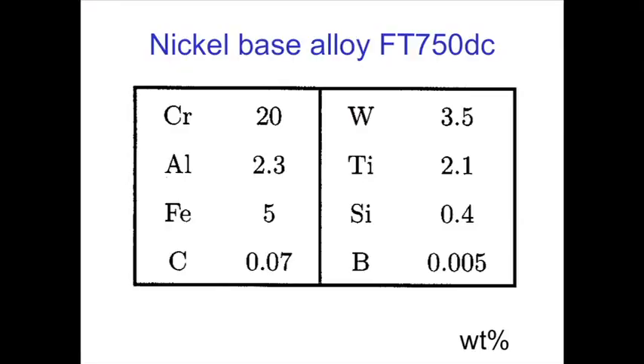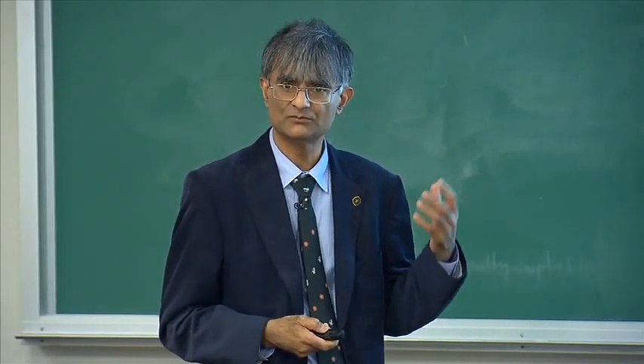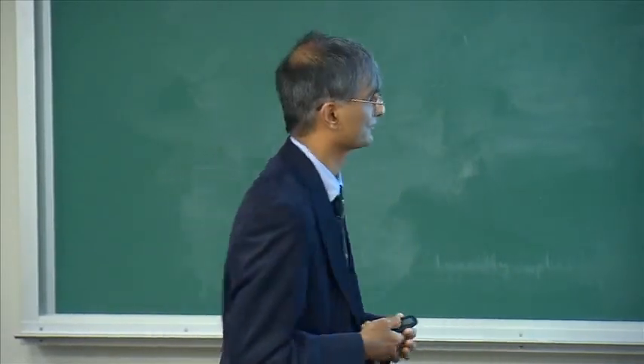So again, we have a very large quantity of data, and we designed a steel using the neural network, not a steel, but a nickel-based alloy. And this is the composition we came up with. Notice there is iron. Iron is not good for nickel-based alloys. But if you allow iron to be there, then the price goes down because you can use scrap material. And it's a much simpler composition than any nickel-based alloy that goes into the aircraft engine. There's no rhenium, ruthenium, and so forth.